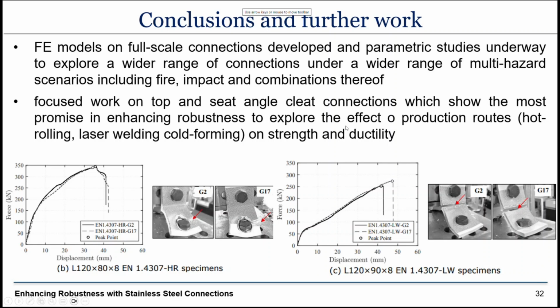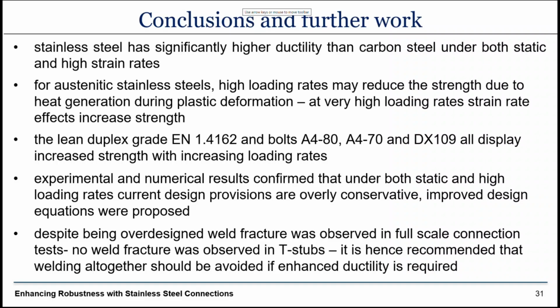So we investigated the effect of having hot rolled angle cleats, laser welded angle cleats, or cold formed angle cleats on the strength and the ductility of the connections at the component level here. And we could see here the comparison between laser welding and hot rolled specimens. We had a change in failure mode. So for hot rolled specimens, we had at very high deformation fracture in the vicinity of the bolt hole over here, whereas for laser welding, we had fracture in the vicinity of the weld.